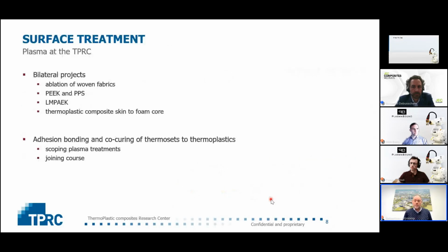Now we have been working with plasma together with Plasmabound on commercial projects. So first we started with, say, the polymer removal procedure in the CPA, where we ablated woven fabric reinforced PEEK and PPS. Now, specifically, PPS is very unreactive to any other chemical substance. And here, with Plasmabound's treatment, we were able to achieve strengths from 0 to 20 for co-cured thermosetting epoxy.